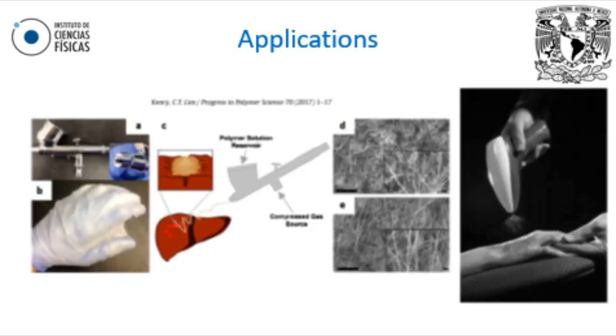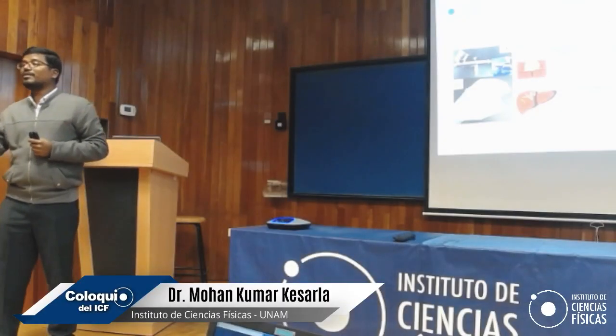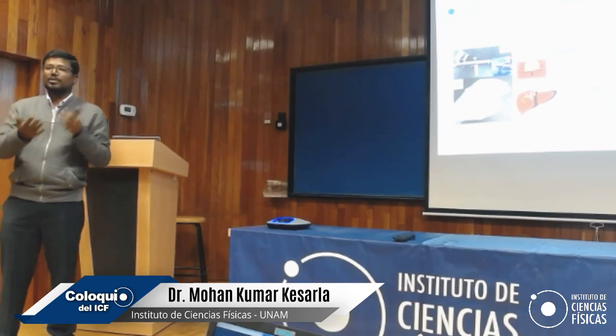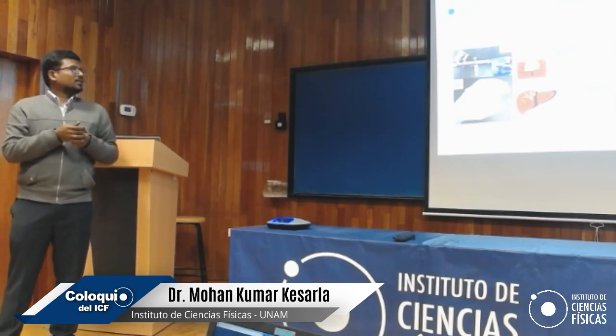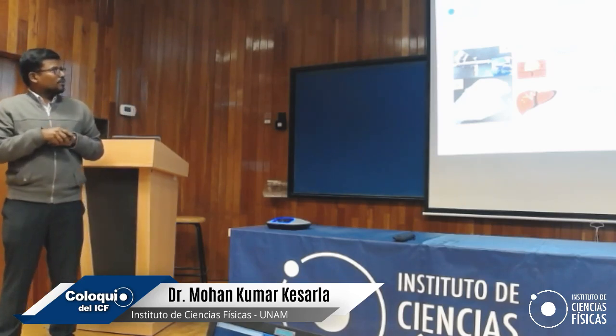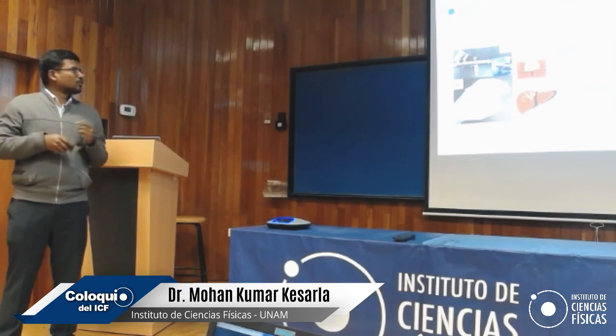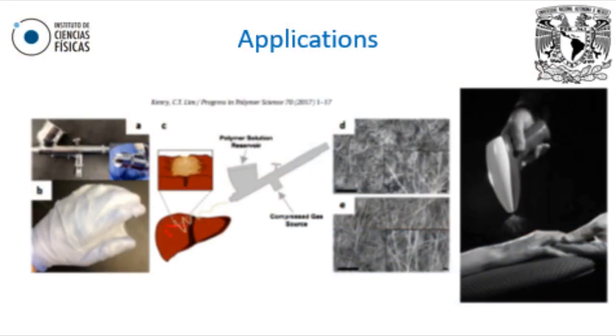And if there are any cuts in any organs of the human body, how do we apply it? So I want to do in situ nanofibers. But the current collector must be conductive in the case of electrospinning. So there was quite a development by Kenry and his group in 2017. What they did is they used a high pressure blow technique to form in situ fibers on the organism.